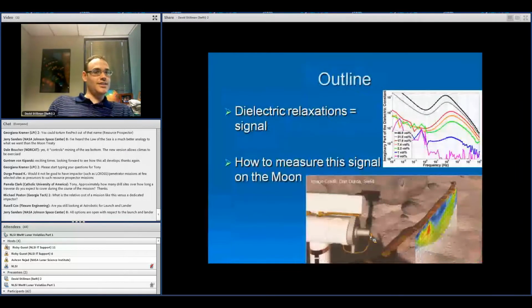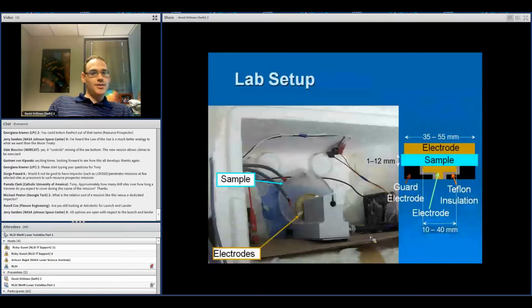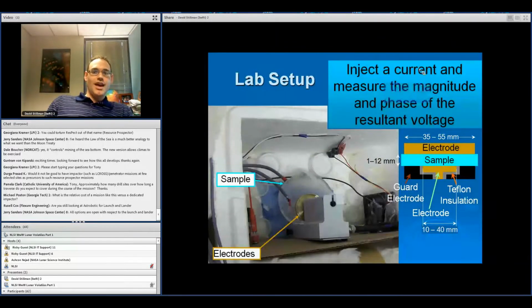So today I'm going to talk about what dielectric relaxations are and how we can use them as a signal, and then how we can measure this signal on the moon. This is our lab setup. This is a picture inside an ultra-low freezer that we can also take down to liquid nitrogen temperatures. We have a sample holder here, a parallel plate sample holder. We put our ice samples, regolith analogs mixed with ice, in here. Then we inject current, and we measure the magnitude and phase of the resultant voltage. Then we change the frequency and do it again. We build up a frequency sweep. Then we change the temperature and do it all again.